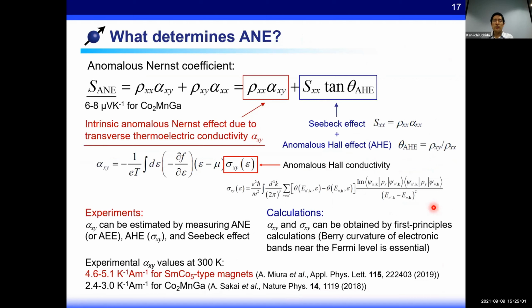So what determines the anomalous Nernst effect? The anomalous Nernst coefficient consists of several transport coefficients, and all of them can be determined experimentally or by first principles calculations. The first term is often regarded as an intrinsic part of the anomalous Nernst effect because it originates from the transverse thermoelectric conductivity alpha xy, which directly converts a temperature gradient into an electric field. A research trend in improving the anomalous Nernst coefficient is to find materials with large alpha xy, in which the Berry curvature of the electronic bands near the Fermi energy plays an important role.